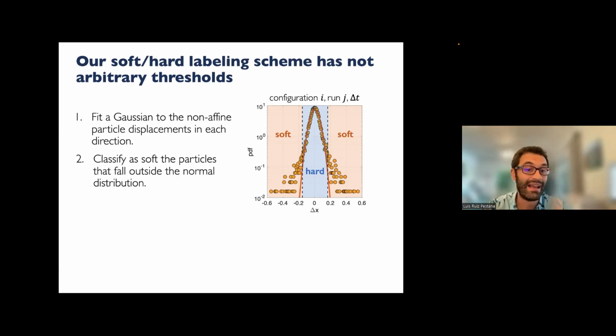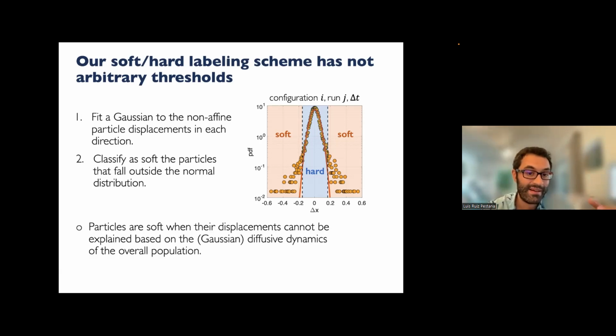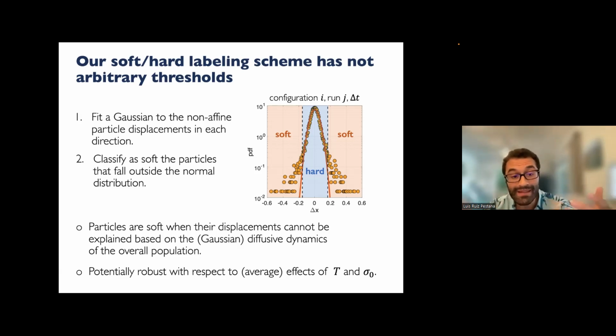So we think, and we have a physical justification, that our labeling scheme is significantly more meaningful than other arbitrary labeling schemes. It offers some very interesting advantages. Here, the physical meaning of our criterion is that particles are classified as soft when their displacement cannot be explained based on the diffusive dynamics of the overall population. And what this can take into account, implicitly, we haven't tested, but it's promising, is effects of temperature or stress that basically affect the whole system similarly, right?